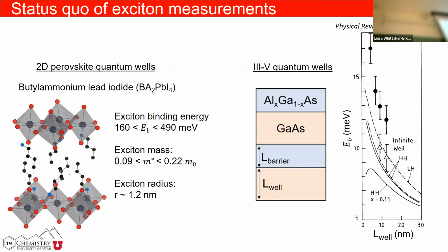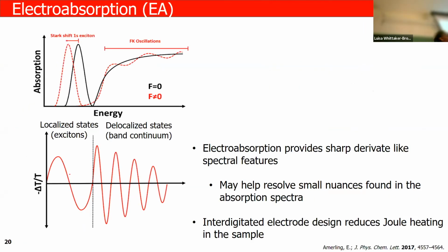So we asked, what are they doing that we are not doing right? What they're doing is using a technique that we had to resuscitate in our lab called electroabsorption. Basically, we apply an electric field and see how the absorption changes. You take the absorption with no field and with field, and you get the change in absorption. You get this signal right here, where at lower wavelengths you have information from localized states, mostly excitons, and then delocalized states, which is information related to anything close to the band gap.